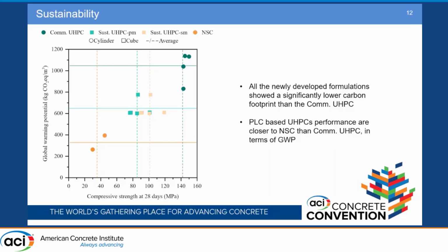As a comparison, if we consider normal strength concrete, we are at approximately a third of that value. But with our formulation, we actually had an average of 640. That meant a reduction of 40% compared to commercial UHPC. And this was important to address the feasibility of our sustainable approach for these formulations.